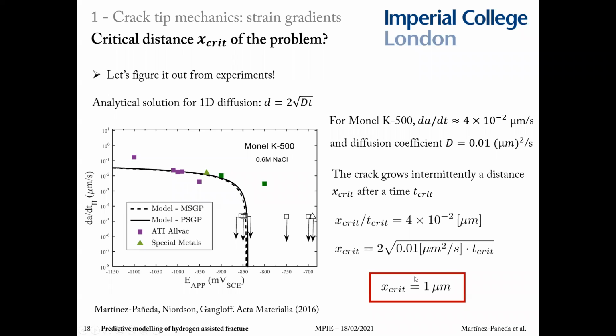Then we can basically come up with a very simple system of 2 equations, the crack speed and the 1D diffusion analogy. By solving this very simple system of 2 equations, we can see that the critical distance equals 1 micrometer. So the hydrogen atoms travel for 1 micron ahead of the crack before reaching that critical region.